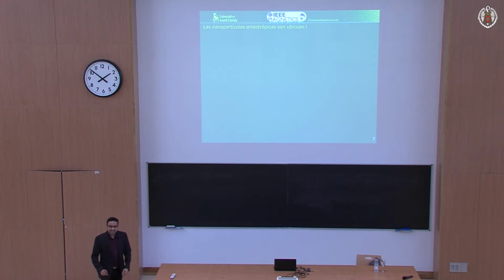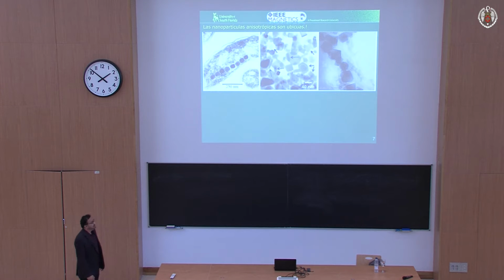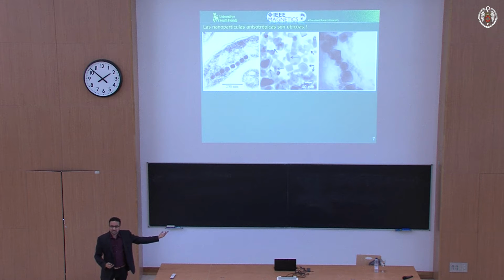Okay, so anisotropy is omnipresent, ubiquitous. That's what hopefully it says in Spanish. It turns out that making anisotropic nanoparticles or nanostructures is actually easier than making perfectly isotropic ones. And it's there everywhere. So just to give you an idea, I'm going to show you 3 TEM images. What you're seeing here, these are all magnetite or iron oxide ferrite nanoparticles of a similar class of materials. And the interesting thing is to see the origin, the source of these TEM images.